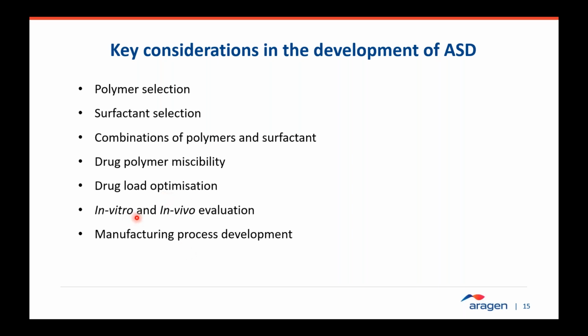In vitro kinetic solubility or dissolution in biorelevant media, and in vivo evaluation in rodent and non-rodent PK studies to confirm the improvement in the bioavailability. And once the composition is selected and confirmed in the in vivo studies, then the manufacturing process is developed, either spray drying or hot melt extrusion, and it is transferred to GMP and then supplied to clinical studies. That's the process. It requires a lot of both solid state knowledge and formulation knowledge to be able to understand how the drug and polymer coexist, and then be able to predict the long-term physical stability of the selected composition.